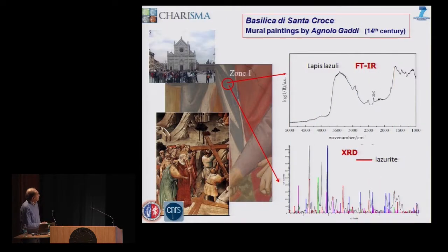Concerning X-ray diffraction, well, it integrates the results, as shown here in this study in Firenze, in the Basilica di Santa Croce. These are mural paintings by Agnolo Gaddi. These are the history of the True Cross. And these are two measurements, infrared spectroscopy and X-ray diffraction, in this zone that is blue, and okay, by FTIR, lapis lazuli was identified through this specific band, and X-ray diffraction confirmed the presence of lazurite.